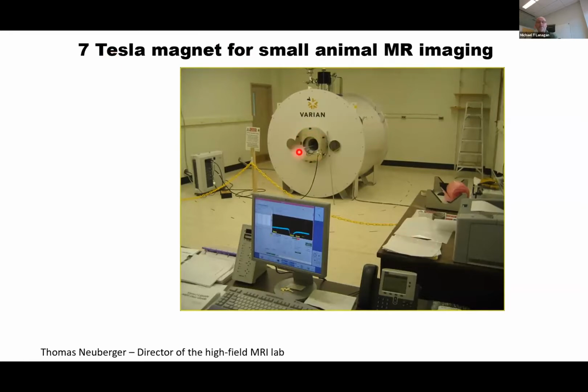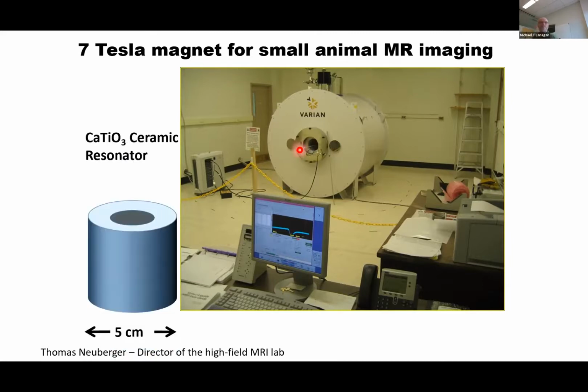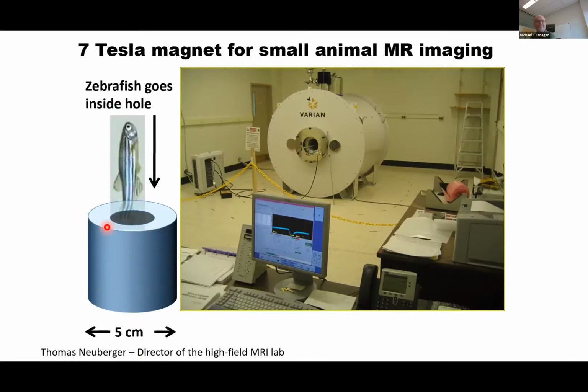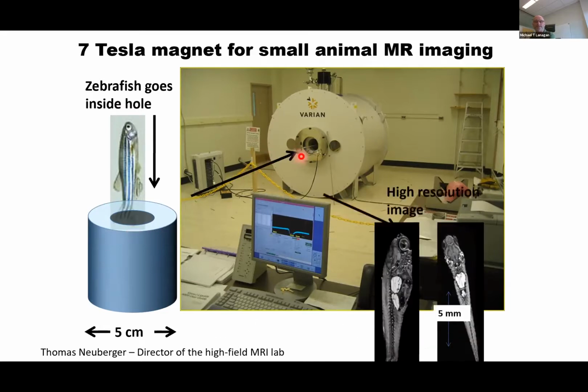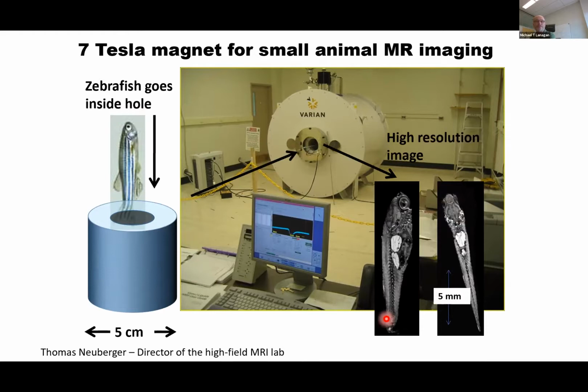Just as an example, this is a small MRI unit that we have at Penn State. The bore size here is on the order of maybe about 20 centimeters, something like that. And so then what we can do there is do animal research. And what we've done is we replaced the coil with a ceramic resonator, and I'll get into why we do that in a little bit. But basically, this supplies the RF field I was talking about. And then what we can do is we can put our samples into this hole here, and then that whole assembly can go into the MRI unit, and we get these really nice images of, say, a zebrafish.